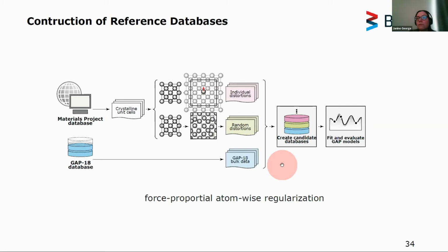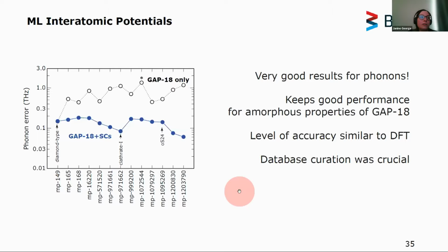And we also did something on the regularization so that these kind of structures where only one atom is displaced could be learned better. And then we were able to arrive at the potential that is really able to capture these phonons. So we were able to reduce this phonon error very much. We were also able to keep the good performance of this model for amorphous properties, and we reach really a level of accuracy that is similar to DFT.